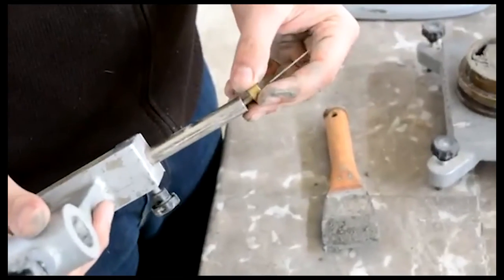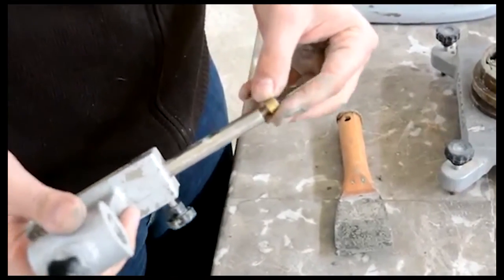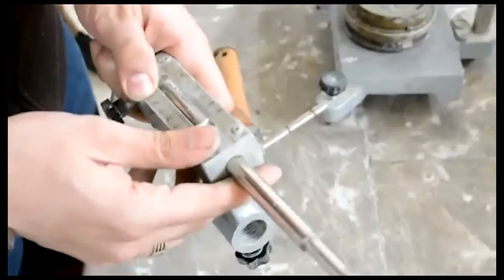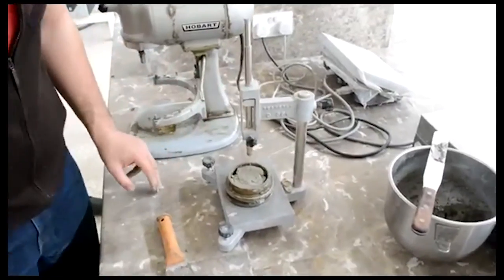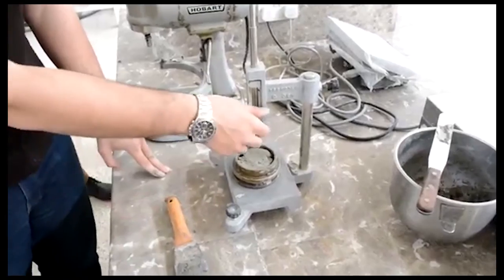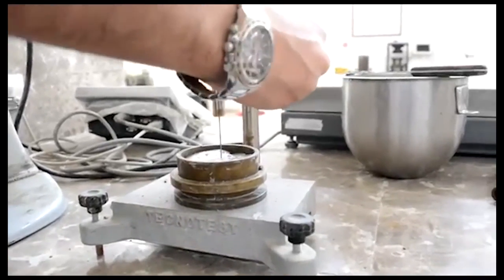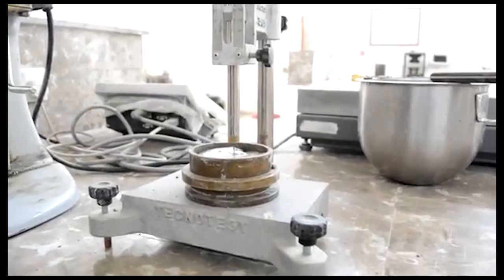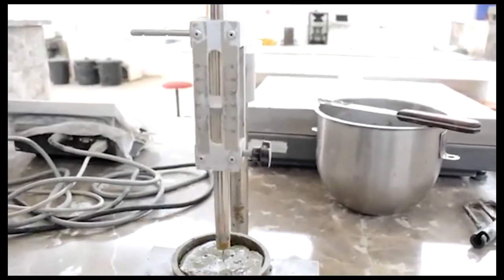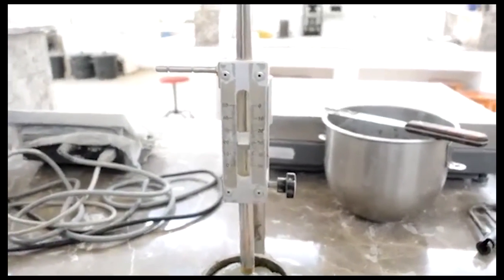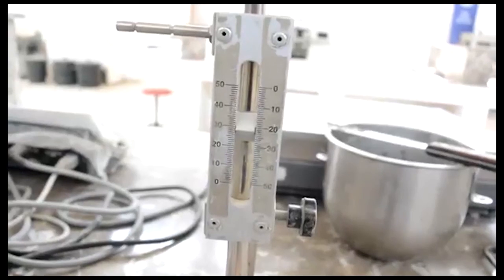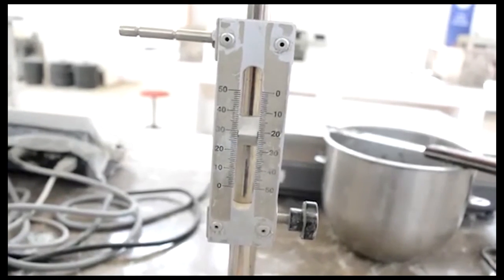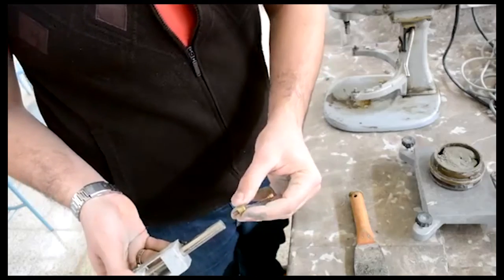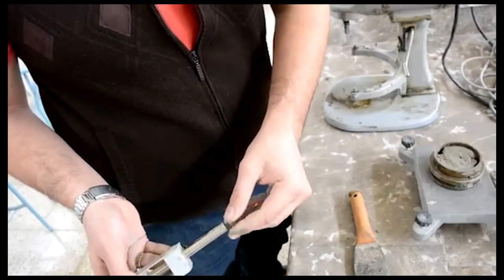Place the thin needle on the Vicat apparatus. Set the indicator on 0. Adjust the needle until it comes in contact with the base surface. Release the needle. The needle will penetrate the paste. Repeat this operation every 15 minutes until a 25 mm or less of penetration is obtained. The time between the initial contact of cement and water and the penetration of 25 mm is the initial time of setting.